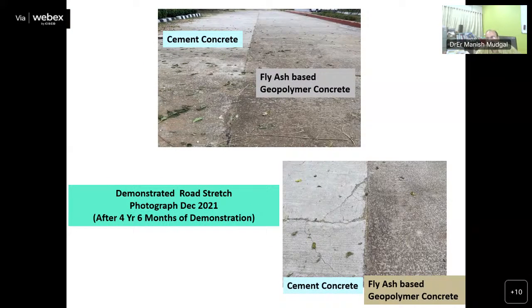Post-performance studies were carried out for 4 years, and these are the photographs from December 2021, of the fly ash-based concrete road, and parallelly we constructed a road with cement concrete. In the fly ash-based geopolymer concrete, the crack pattern is very minimal, shrinkage is low, thermal expansion is low. Because of this, we could make a very durable road for all weather conditions.